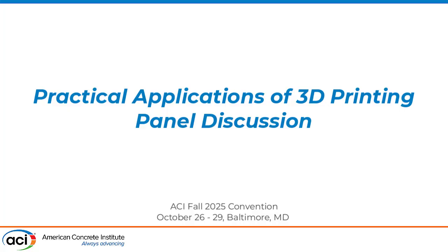Nice. Appreciate the comments. And you kind of, let's say, foreshadow this other aspect that I feel like it's worth sharing. When we were doing our testing, we're working with a commercial material that has roughly a layer time of 3 minutes. And it didn't matter if we were programming our Z step-up height, so our layer height, to be 15 millimeters or to be 25 millimeters, which is almost double. We were seeing roughly the same layer time. And so the layer height didn't proportionally increase the layer time, as I would normally think, because you're putting more material, you have to wait more time for the material to cure. There does seem to be this weird thing where, even though your layers are growing, you still have to wait a similar amount of time.